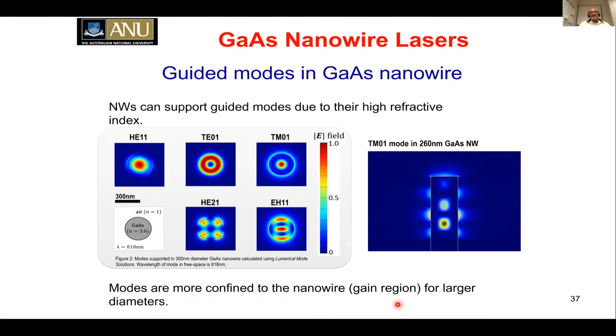First we design these nanowire cavities so that we can identify what the height and length of the nanowire should be, and what the diameter of the nanowire should be. This is the work of Drew Saxena, where he has looked at the various optical modes which propagate in a 260 nanometer gallium arsenide nanowire. And he is demonstrating this particular optical mode, which has the highest intensity at the center of the nanowire, for example.